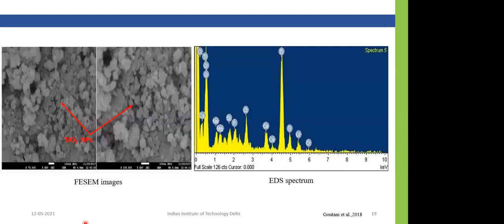Even the SEM analysis was also performed in that particular study to determine the shape and estimate the average grain size of the green synthesized TiO2 nanoparticles. So these images show the green synthesis of spherical shaped TiO2 nanoparticles with a diameter ranging from around 10 to 20 nanometer. The energy dispersive X-ray spectroscopy (EDS) was employed to know the elemental composition of the green synthesized nanoparticles, and the EDS spectrum revealed the purity of the sample as both titanium and oxygen were present in the sample. So this further confirmed the green synthesized TiO2 nanoparticle formation.